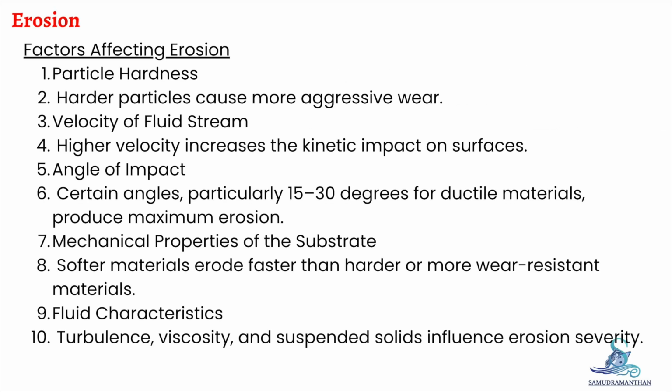Several factors influence the severity of erosion. Particle hardness plays a major role. Harder particles cause more aggressive wear. The velocity of the fluid stream is another key factor. Higher velocity increases the kinetic energy of particles, leading to more severe erosion. The angle of impact is also important. For ductile materials, angles between 15 and 30 degrees produce maximum erosion. The mechanical properties of the material matter as well. Softer materials erode faster than harder or wear-resistant materials. Finally, fluid characteristics such as turbulence, viscosity, and suspended solids significantly affect erosion severity.